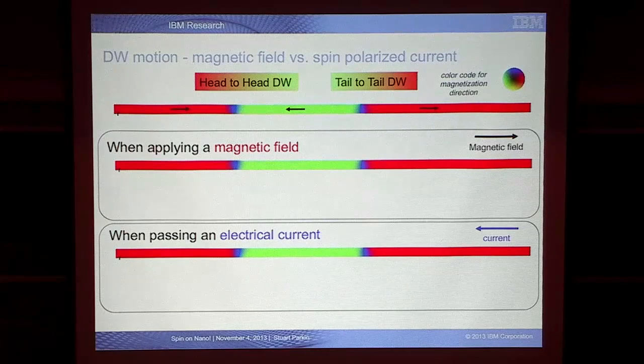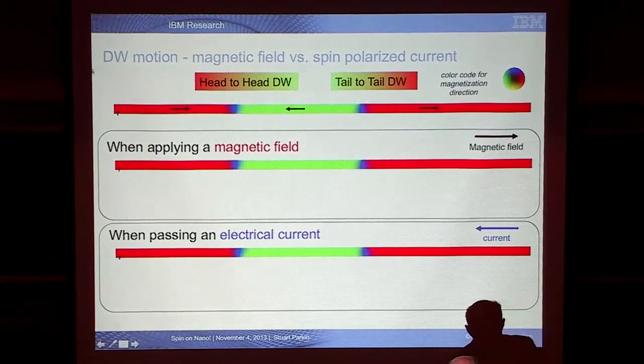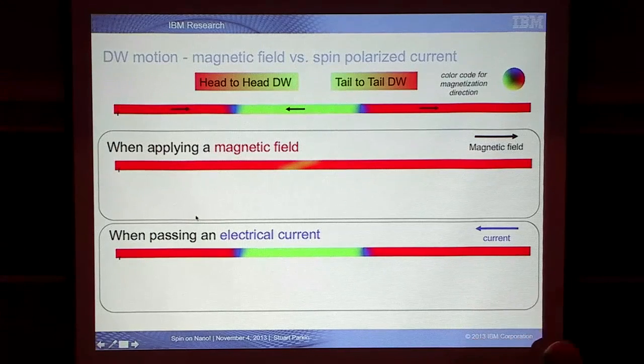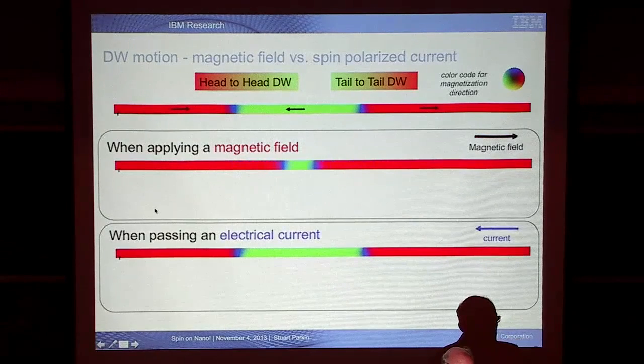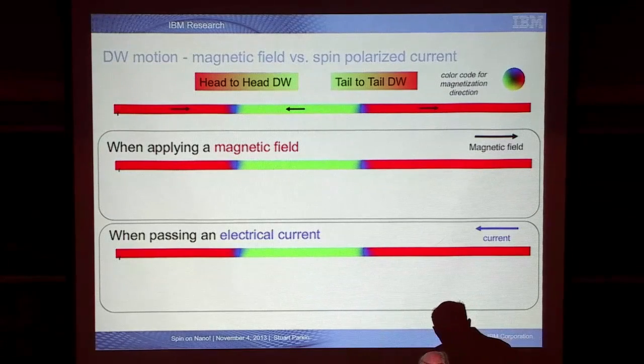Inevitably, at the next domain wall, you see these two regions have their north poles pointing away from each other. Now, until just a few years ago, the only way of manipulating the magnetic moments in this wire was to apply a magnetic field. If you apply a magnetic field, like all compass needles, the north pole will rotate towards the field. Same thing happens here. We can simulate that just by solving some equations. And what you see then is the two domain walls will move together because the magnetic field favors this red direction. Does that make sense? So we just go back, and you see the red regions will grow because the magnetic field will favor all the compass needles to point in the red direction.